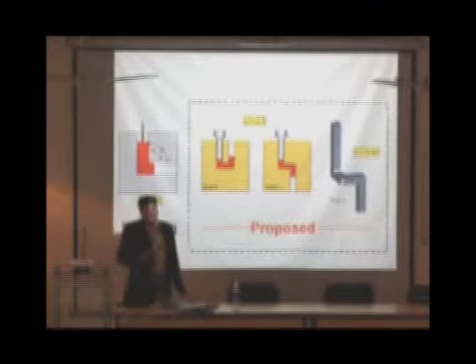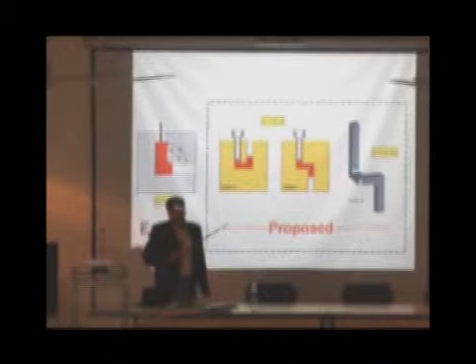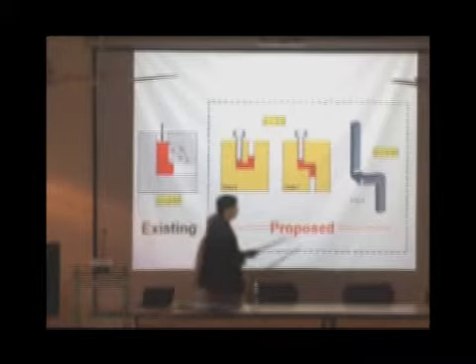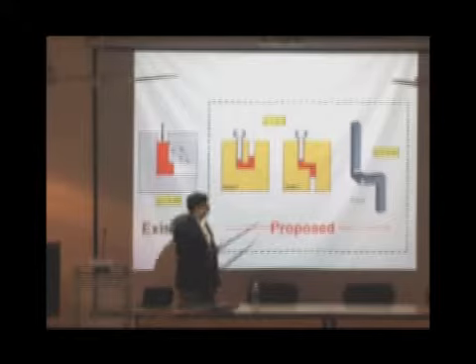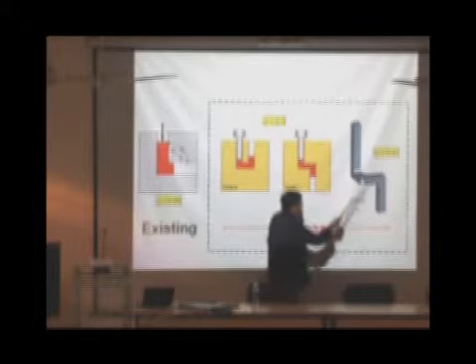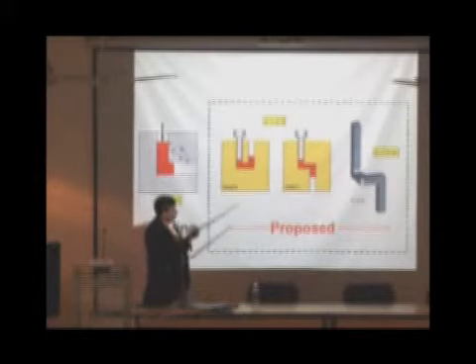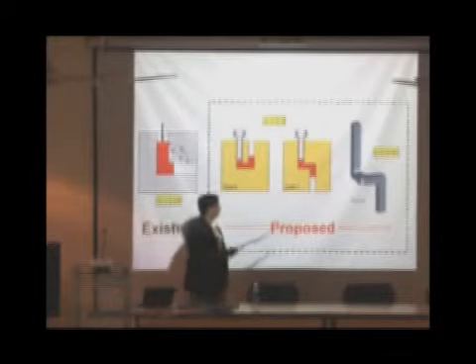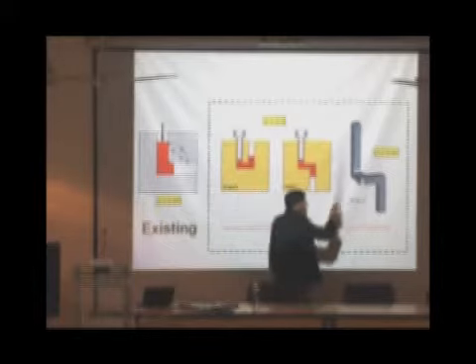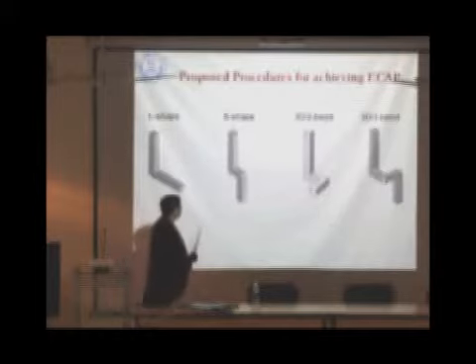What we are trying to overcome is that we don't have to repeat this process again and again, and this can be continuously applied. Then it can be called as a continuous ECAP, and this process has got commercial viability. In a single pass we are getting strain of 2.3, but with multi-turn we are getting strain of 3.45. I will show you some simulations.